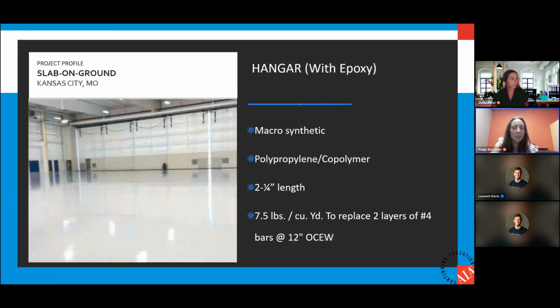And then for this next one, just another hangar option showing how we can put an epoxy on top as well. Just keep in mind that we can do up to 7.5 pounds of dosage with these microfibers. They're dosed anywhere between 3 pounds and 7.5. Anything over that amount might get hard to finish. So we would consider a steel fiber at that point, and Dylan might take over the project. Typically for workability and constructability, we will recommend the steel fiber if we're getting above that 7.5 pound dosage on the synthetic side.